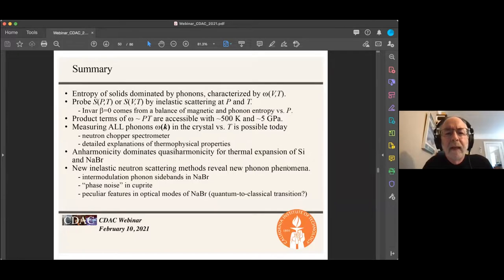And we can understand its zero thermal expansion as coming from a cancellation of the magnetic and phonon entropies in the material. A special case there, INVAR. Now, I think in a more general case, we can look at how these frequencies depend on the product of pressure and temperature. If we can get a range of 500 Kelvin and about a range of 5 GPa simultaneously, I think we can do some really interesting studies of new features in how anharmonicity changes with volume or how Grüneisen parameters change with temperature.